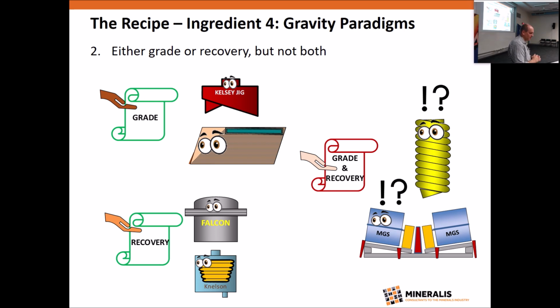Number 2. Each gravity unit process should be given one task only to perform, either grade or recovery, but not both. And again, the high G-force concentrators are a good example in gold and base metals. They're there for recovery. And grade and recovery really can only be achieved in one step if you've got a very coarse liberation size, there's a very narrow size range, and there are no competing minerals.